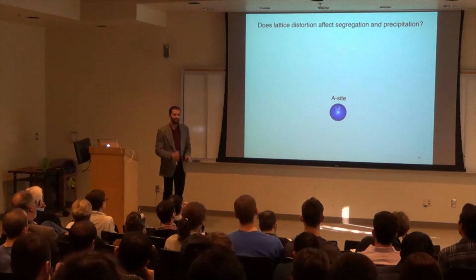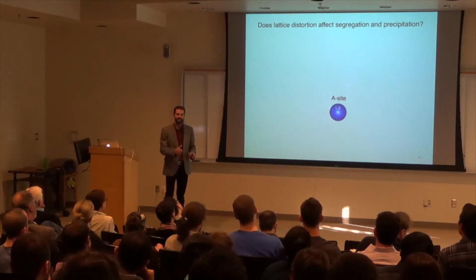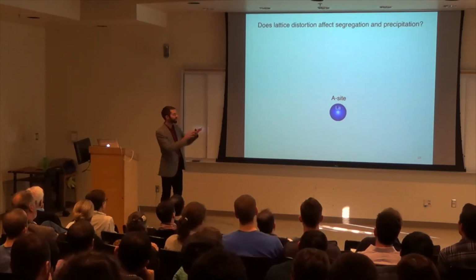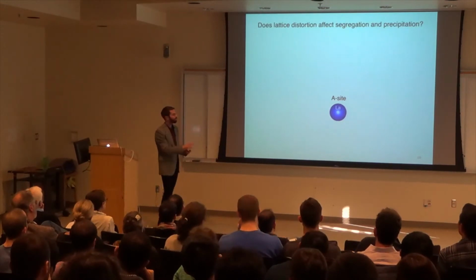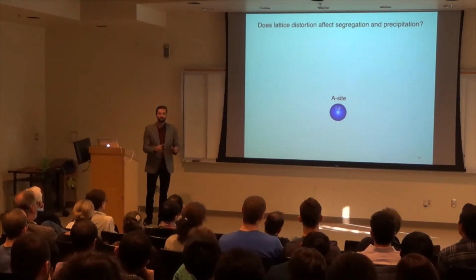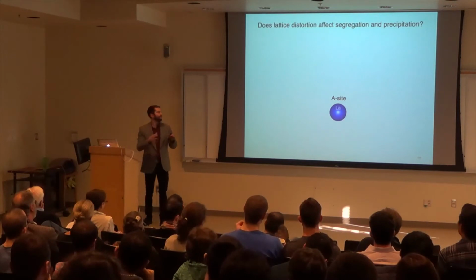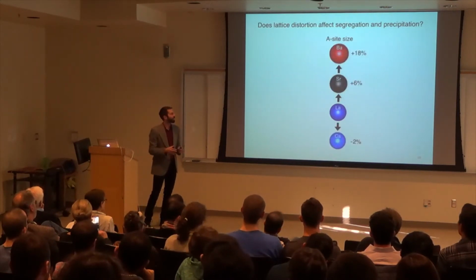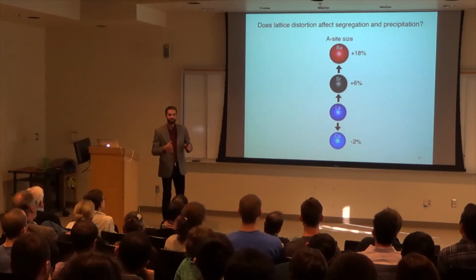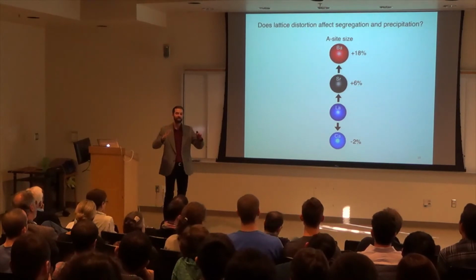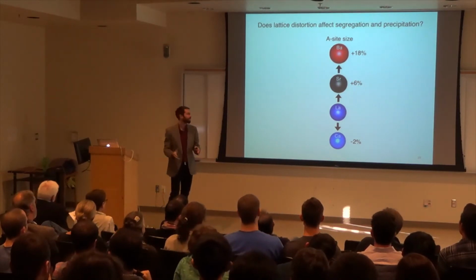And so what we do is we focus on the A site. Remember, it's not the transitional. This is just the A site where the lanthanum is. And what we're going to do is distort the lattice by putting in alkaline earth elements of different sizes. We're going to expand the lattice and see what effect that has on segregation and precipitation.